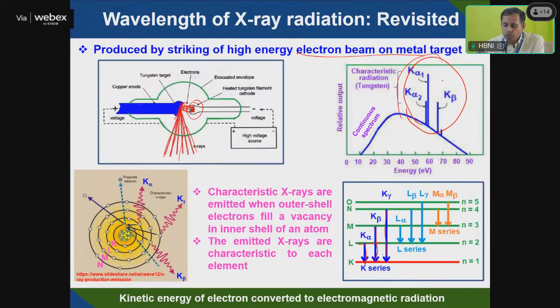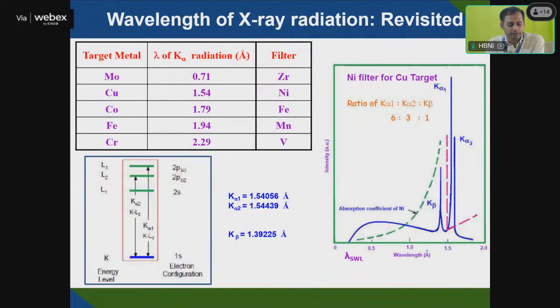And you know that when you go for an X-ray diffraction study, first of all you remove the K beta by using a filter. That Z-1 principle I discussed: if your target is copper, then the filter should be nickel. The atomic number should be Z-1, the previous one you will use. And then K alpha 1 and K alpha 2 will be there, quite overlapping each other. So in conventional XRD, you can't differentiate between these two, but by using a high energy synchrotron source, you are able to eliminate K alpha 2. So this characteristic peak is mainly what is important for X-ray diffraction studies.